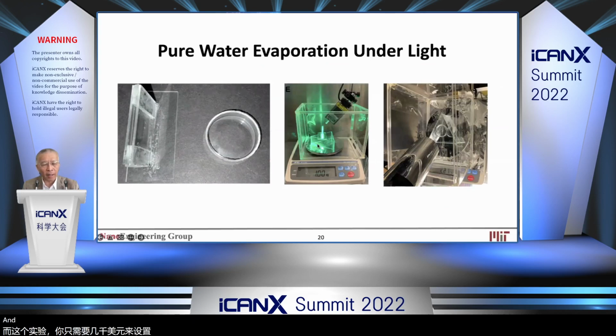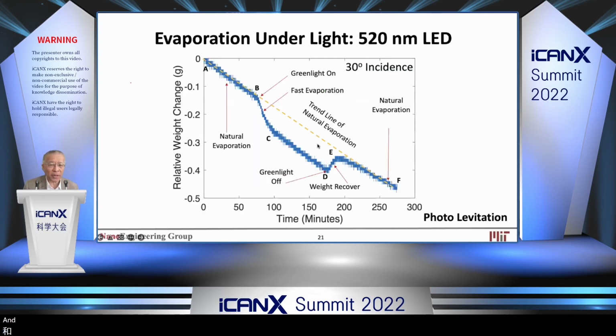And the evaporation, we took a green light first, 520, at the angle of incidence 30 degrees. And this is the weight, measuring the weight loss. From A to B is natural evaporation. There's no light. At point B, we turn on the light. And we saw B to C. This is amazing to us. We saw the weight rapidly drop, but the rate slowly decrease. Come to C and D, they are almost parallel to A and B.